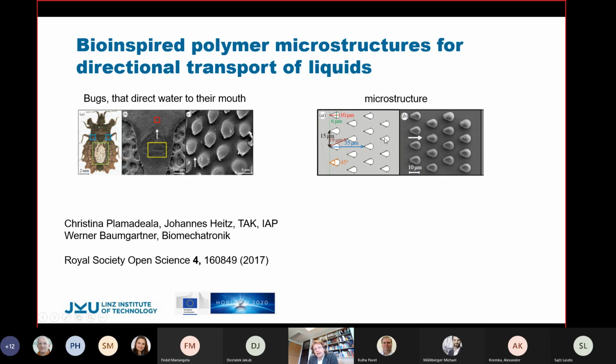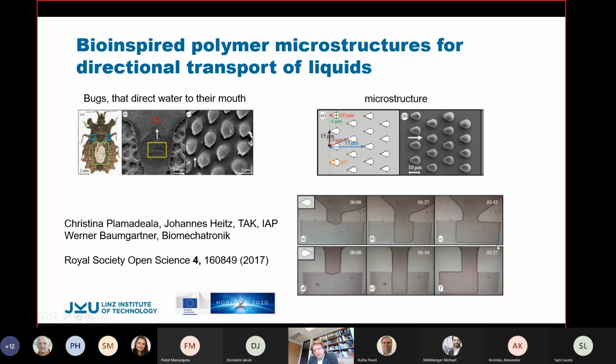Taking that as an example, we were writing these 2.5-dimensional structures, very similar to the biological original, and down here, this light gray area consists of that kind of structure. Depending on which direction these small parts point, when we apply an aqueous solution or some liquid, you can direct the liquid to the right, or if you turn the whole thing around, you can direct the liquid to the left. So you can direct the flow of the liquid as it is done by this bug.